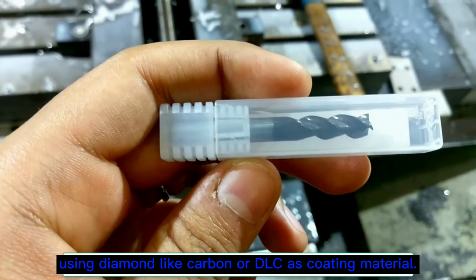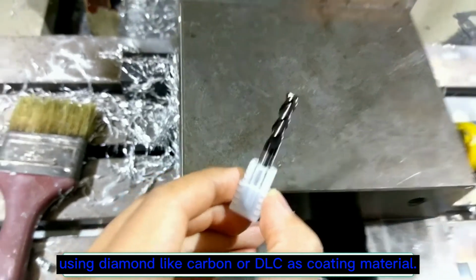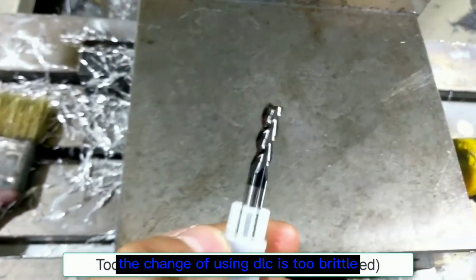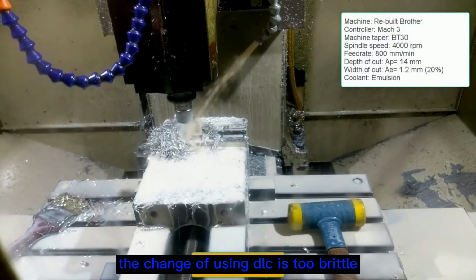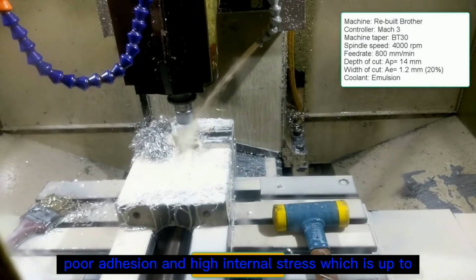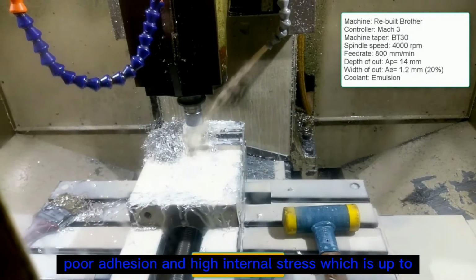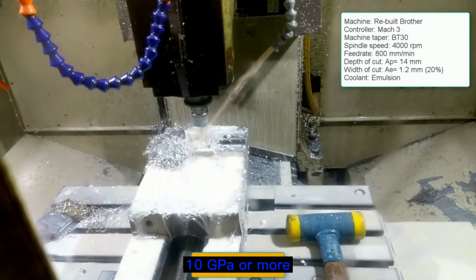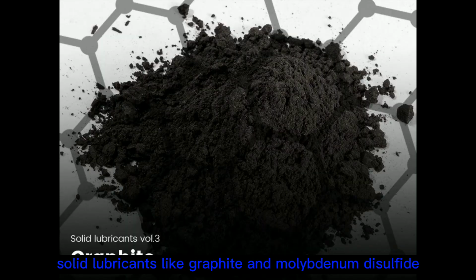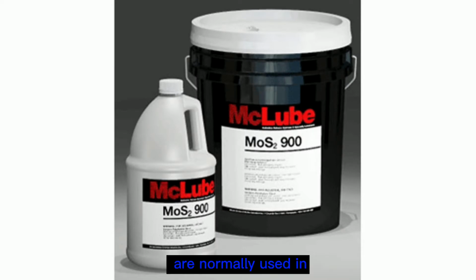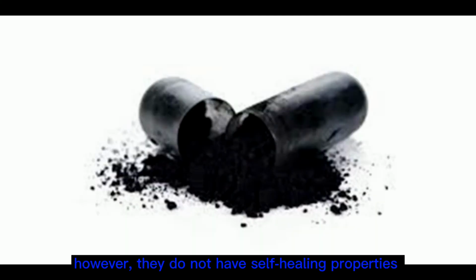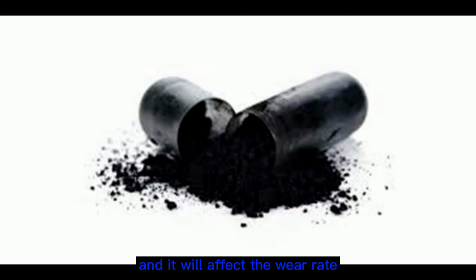Besides, some coatings use diamond-like carbon, or DLC, as coating material. The challenge of using DLC is that it is too brittle, has poor adhesion, and high internal stress, which is up to 10 gigapascal or more. Solid lubricants like graphite and molybdenum disulfide are normally used in machining industrial parts. However, they do not have self-healing properties and it will affect the wear rates.